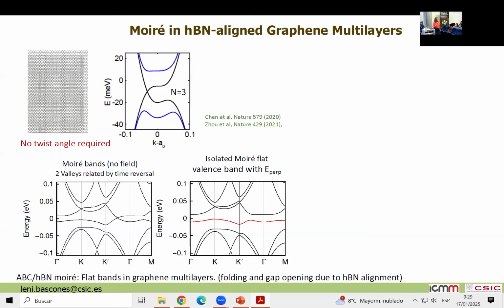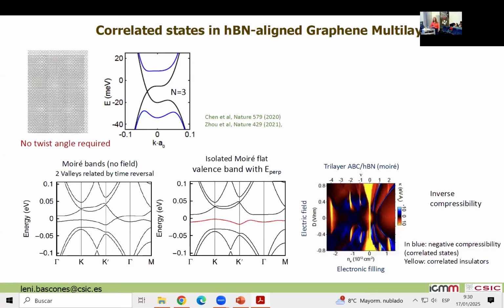Now, here there is also another tuning knob, which is the perpendicular electric field. In some systems, the bands are going to be very sensitive, and we can even open band gaps by putting in a perpendicular displacement field. So you can see here, for example, how this band changes from here to here. So here you see we have this isolated band. Then quite soon people also observed correlated states, insulating states, in this rhombohedral trilayer aligned with boron nitride. Okay, this is not twisted bilayer graphene, this is another system.